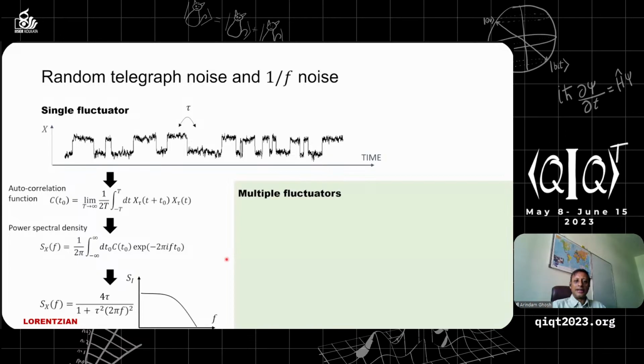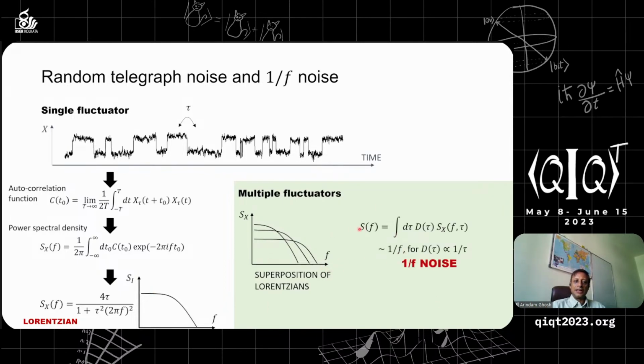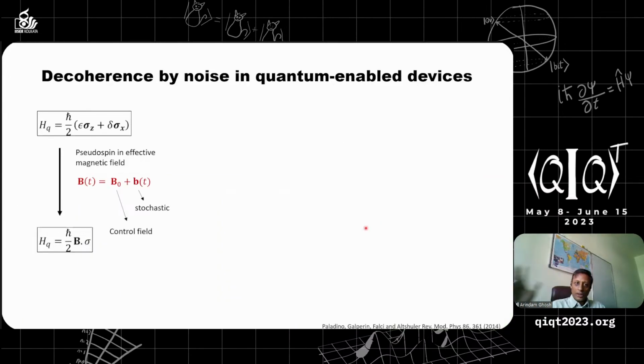Okay. Now, in a real system, of course, there are multiple fluctuators. There's not one. And those multiple fluctuators will flip at different time scales. So you need to add them all up. You need to add all the Lorentzians of different time scales. And then if you add it properly, you will see that the frequency dependence of the power spectral density goes as 1 over f. Okay, and this is called 1 over f noise. Why am I worried about 1 over f noise? Because as the frequency goes to 0, the noise actually diverges, or becomes very, very high.